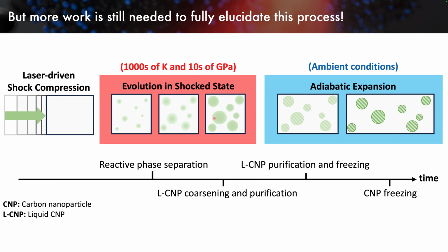At some point, that compressive shock wave is going to move out of your sample, and that's going to cause it to adiabatically expand back down to ambient temperature and pressure, and that's going to drive solidification of those liquid carbon nanoparticles. The nature of those nanoparticles are going to be controlled by things including the initial state that you quenched from, the rate of that adiabatic expansion, the composition of the particles when you began and are undergoing that expansion, and so on. So it's a pretty complicated process.